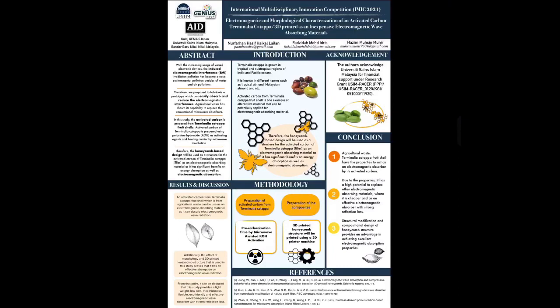For the materials and method, the first is preparation of activated carbon from Terminalia Catappa. The husk is removed from the fruit and the shell of the fruit is soaked in distilled water for a night. The fruit shells will be crushed and dried at a temperature of 100 Celsius for 24 hours. The dried shells are crushed into a size of 0.1 to 1 cm.